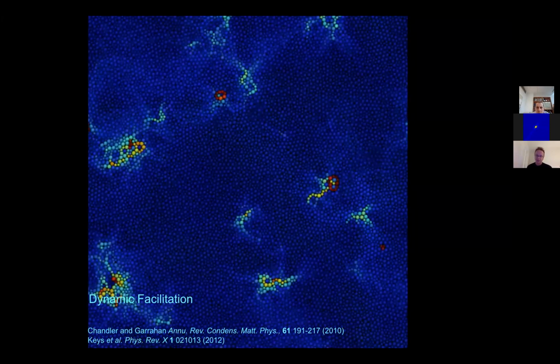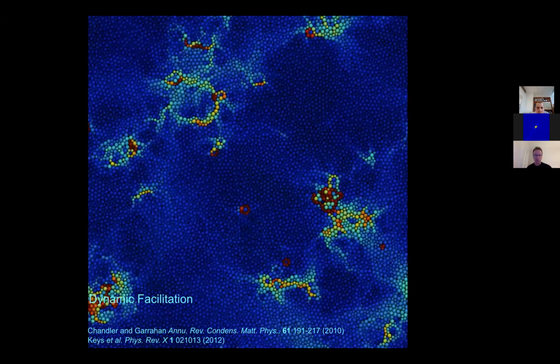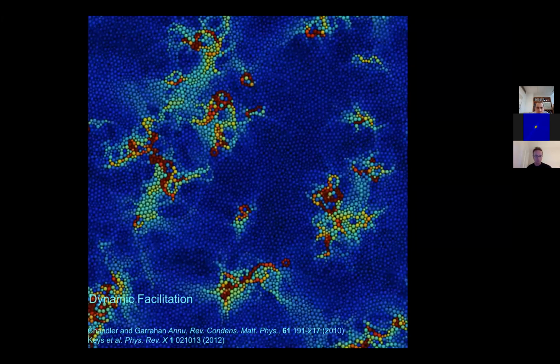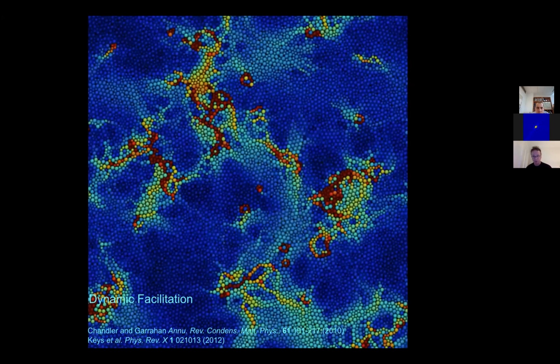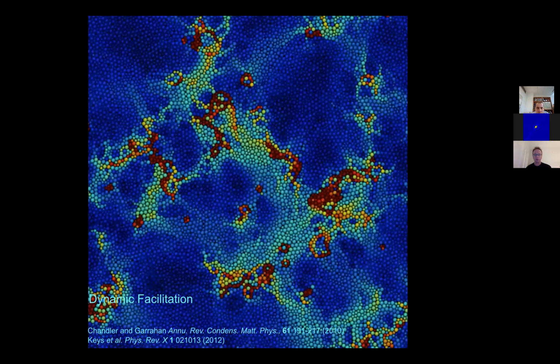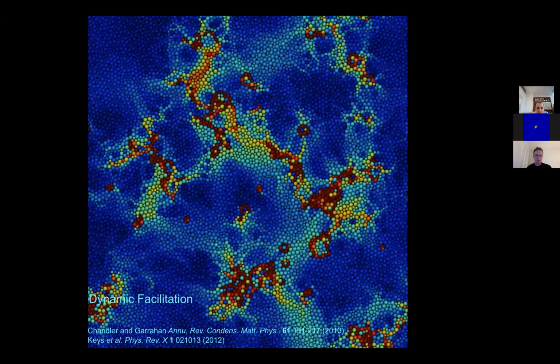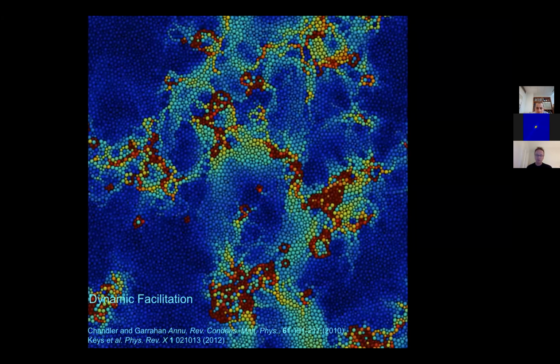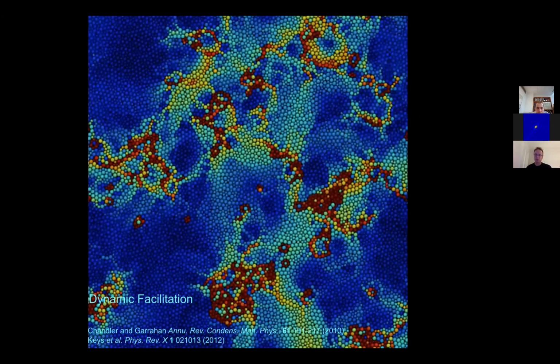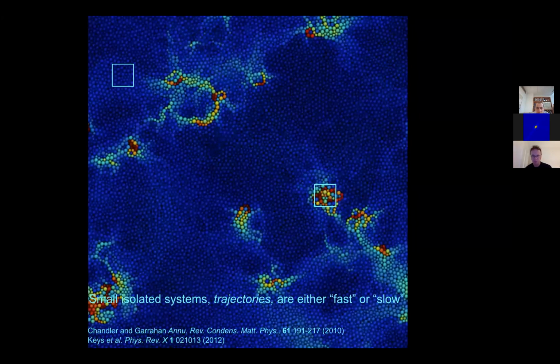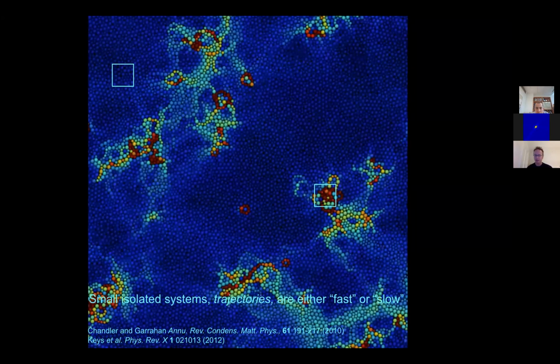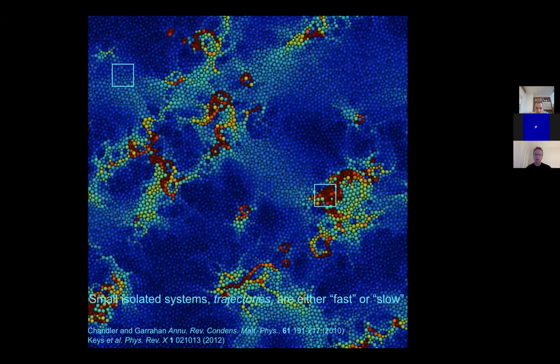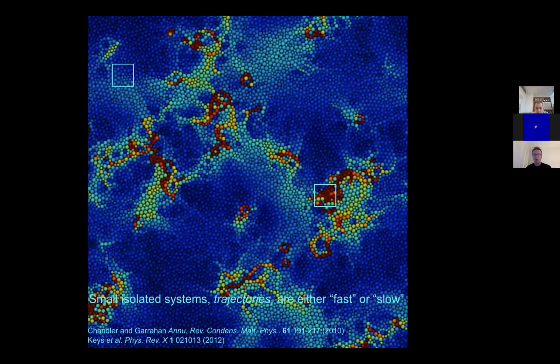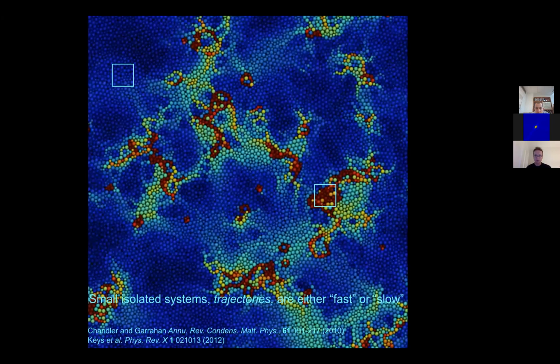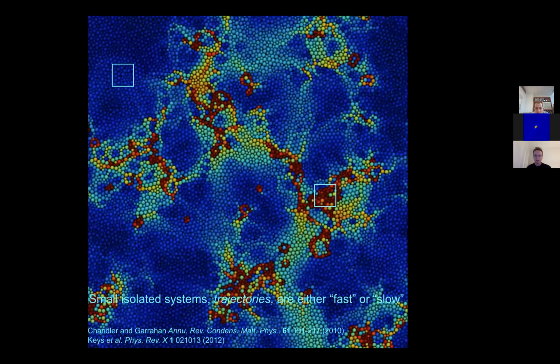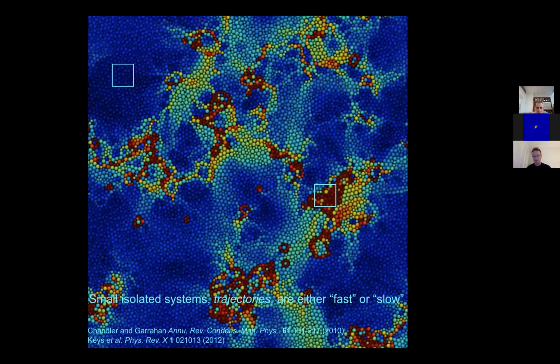So what we see is that the particles move, but crucially, they do not move all together. Some of them move, the red ones have moved the most, and the blue ones have not moved. But in no sense do they move all together. In fact, what we could do is we could think of a small region, and we're going to call a small region a trajectory. And these trajectories, well, the one on the top left has not moved. The one lower down on the right is moving a lot. It is as if it's a liquid.